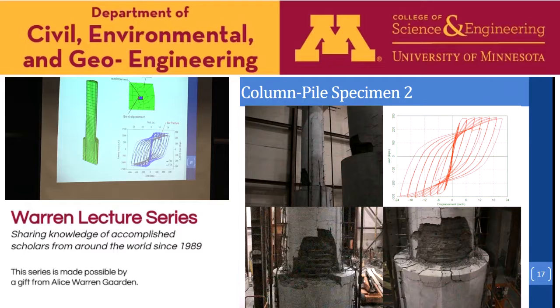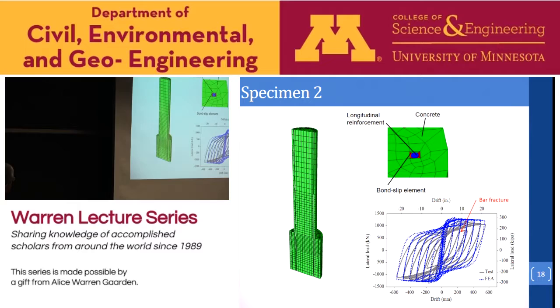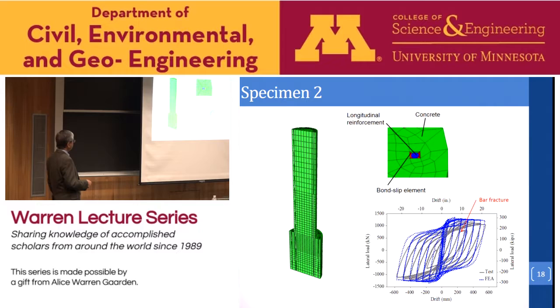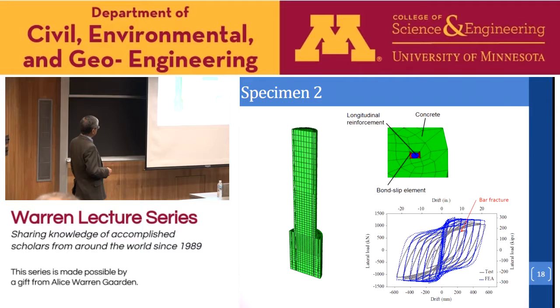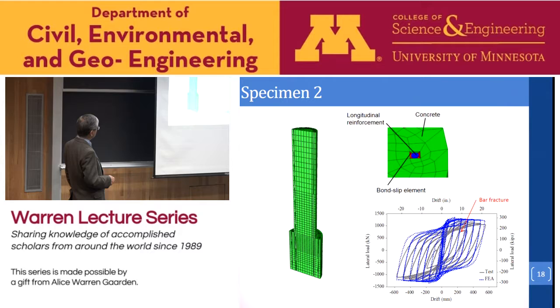So we did 3D finite element modeling using the Abaqus program. We implemented our bond slip law there. So we can see that we can mimic the behavior very well. One thing we did not capture is the load degradation and also the rupture of the bar, because in Abaqus, the steel model is not able to account for the bar fracture.